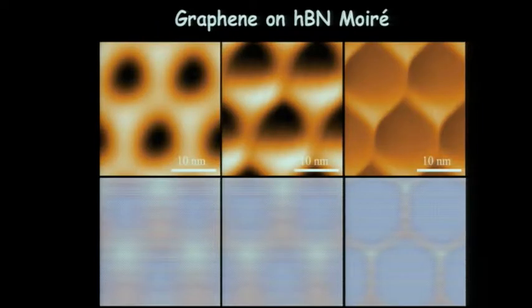To us, that looked a little bit like what we were seeing here in our STM images. We went from some kind of smooth landscape to a much sharper landscape over here. And so we wanted to actually go and see, do we actually see this strain in the graphene? So the difference in the top row is only the distance of imaging? Yes. What's that got to do with the strain of the sample below? I'll come to it. The tip is basically interacting with the graphene and changing the interaction with the substrate.